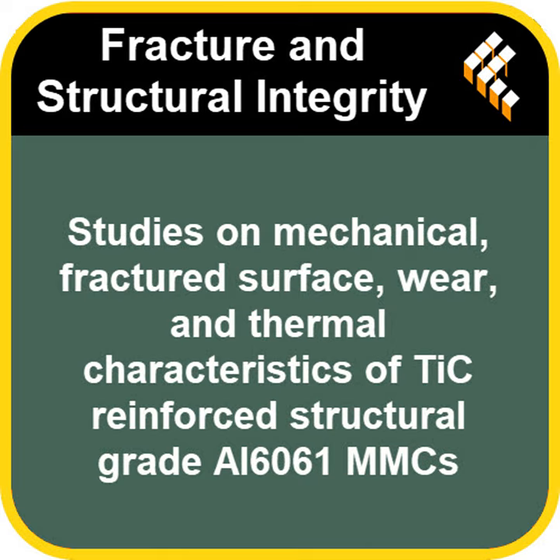And once they had these solidified samples, what did the optical microscope reveal? What did the internal structure look like? Well, what's fascinating here and really encouraging from a materials perspective is that their microstructure analysis showed the TiC reinforcement was remarkably uniformly distributed, evenly spread out within the aluminum matrix. That sounds important. Oh, absolutely critical. This uniform dispersion is key for the composite's overall properties. If the particles clump, you get weak spots.